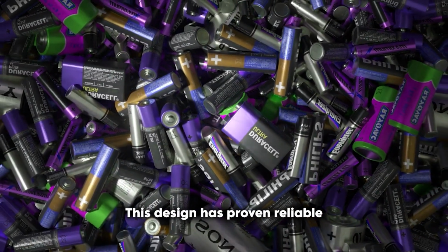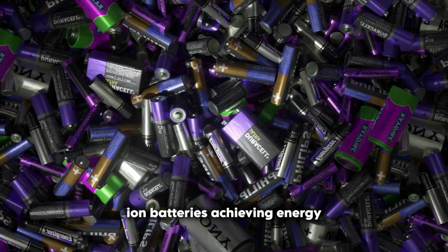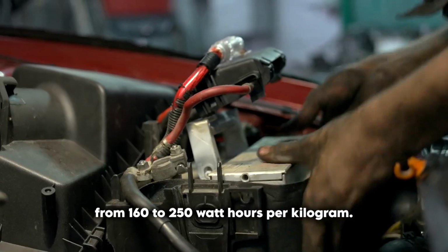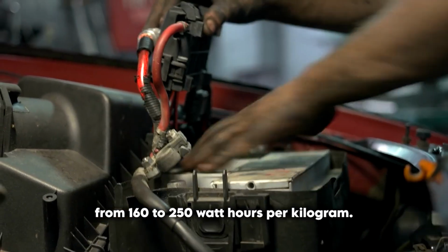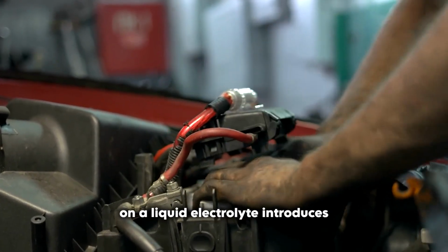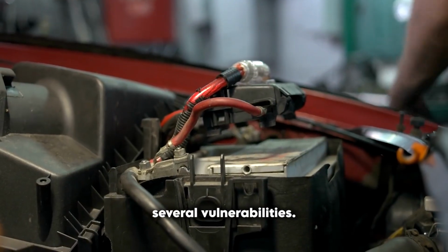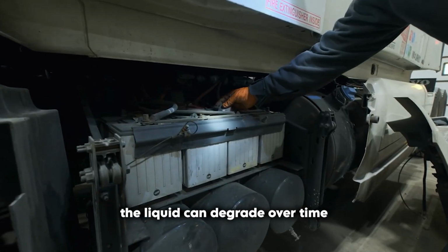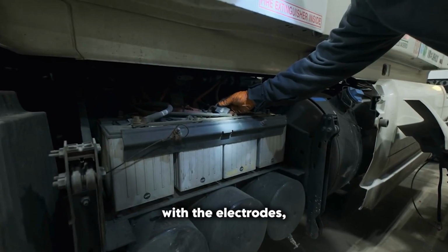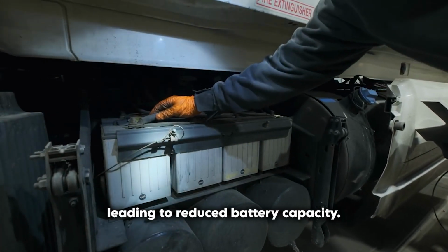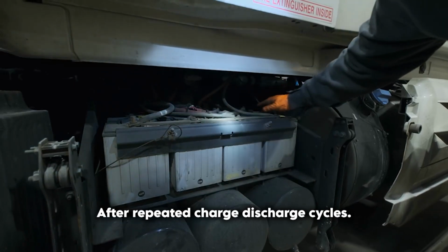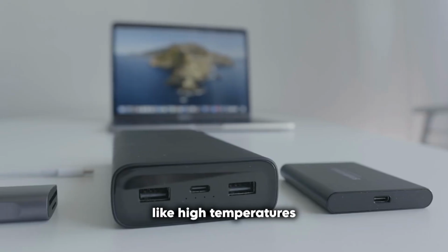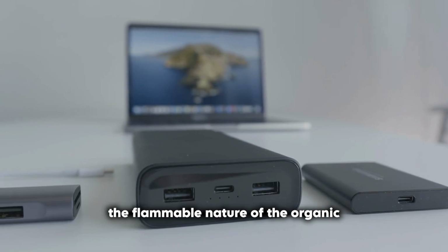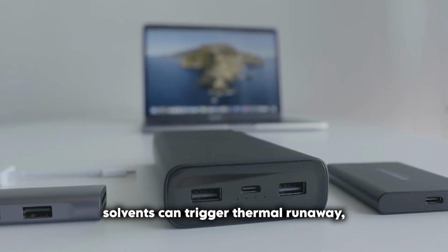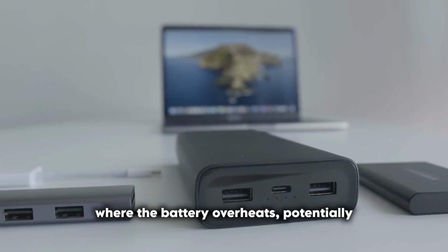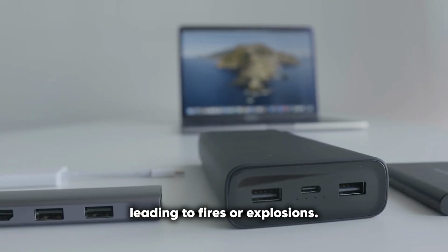This design has proven reliable and scalable, with current lithium-ion batteries achieving energy densities ranging from 160 to 250 watt-hours per kilogram. However, the reliance on a liquid electrolyte introduces several vulnerabilities. For instance, the liquid can degrade over time due to chemical reactions with the electrodes, leading to reduced battery capacity after repeated charge-discharge cycles. Moreover, under extreme conditions like high temperatures or physical damage, the flammable nature of the organic solvents can trigger thermal runaway, a chain reaction where the battery overheats, potentially leading to fires or explosions.